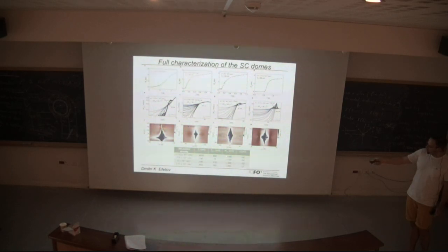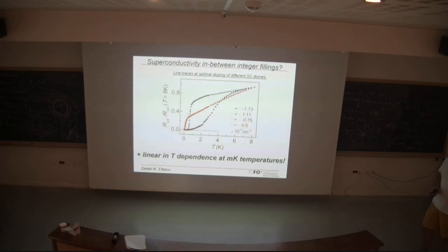We extract HC2s, and we extract, for example, Xi, the coherence length, which is usually on the order of 20 to 50 nanometers. So the coherence length which we extract is only several unit cells, 2 to 3 unit cells of the moire. Again, this is just for you to check. This is resistance as a function of temperature. We get this linear temperature dependence for all of the states, down almost to 100 millikelvin, which is debated as to whether this is the strange metal phase. And then in all of these states, the resistance drops to 0.